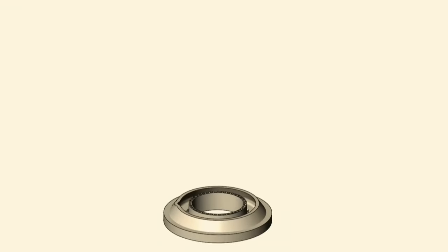So once you've made the part in the laser bed and it's surrounded by a load of unmelted powder and you've dusted it out, you pull it out of the bed and you then have to heat treat it to relax all the internal stresses. So what we can do is design an engine for 3D printing, and this is what we did.